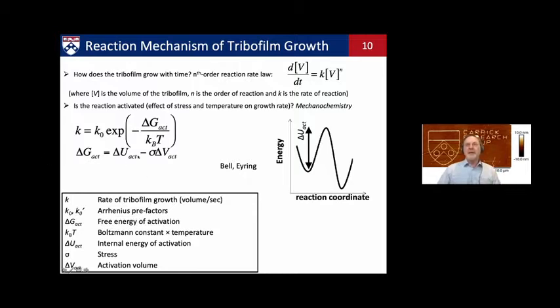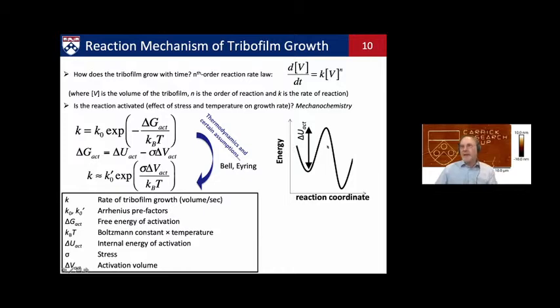They postulated that you have a linear effect, a linear change in the activation barrier with the applied stress. And if you plug that linear dependence in, you get a prediction that the reaction rate should vary exponentially with the applied stress. So on this energy diagram, what we're saying is the stress you apply multiplied by an activation volume, which represents the volume that's being affected by the stress that drives the reaction, reduces the activation barrier. So you get this exponential benefit from applying stress.